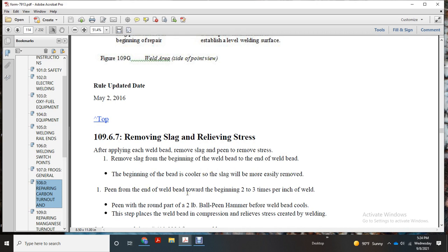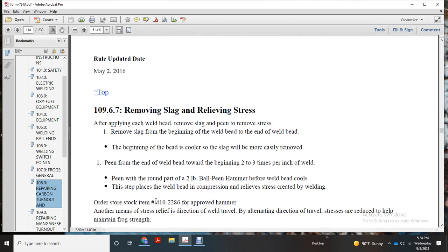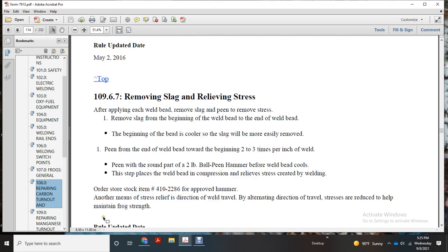Peen from the end of the weld bead toward the beginning, 2 to 3 times per inch of weld, using the round part of a 2-pound ball-peen hammer before the weld bead cools. This peening places the weld bead in compression, relieving stress created during welding. Order stock number 410-2286 for the approved hammer and other means of stress reduction.